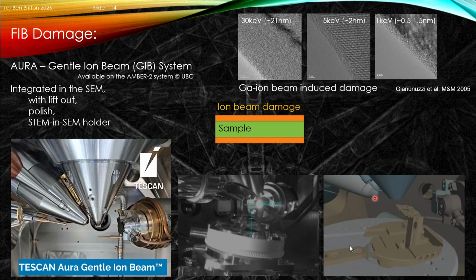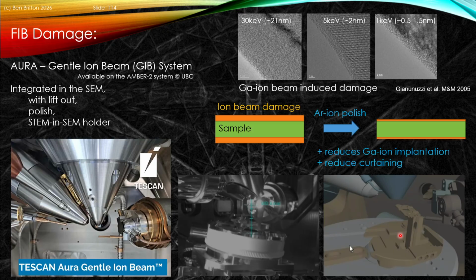plasma, and that enables us to effectively polish our material to remove layers at a glancing angle, and we can use the stage to sweep the sample to reduce so-called curtaining artifacts. What's really cool here is that we can now remove more and more of that surface damage layer, and we can polish down to say a 200 electron volt thickness with an argon ion. So that's effectively, remember that the argon ions have a very short stopping distance and don't tend to alloy in those systems. And the broad ion beam plus the rocking enables us to reduce the so-called curtaining artifacts.